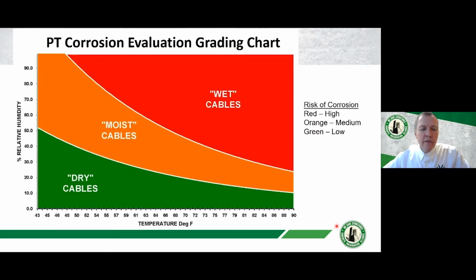We can then take that information and plot it on a table like this. This is a multi-temperature version of the table that I showed you before with the one simple curve. Based on the temperature and the relative humidity, you can determine whether you are in a high, low, or medium risk condition. So if you take a measurement down here and you're in this green zone, then your risk of corrosion is low. And honestly, you probably don't have any significant issues with regard to corrosion at all.